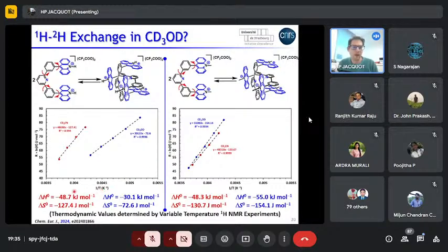Also, we have exactly the same thermodynamic parameters for both systems in acetonitrile and a huge change in methanol. So what we hypothesized is that methanol allows proton-deuterium exchange for the N proton of acridine and protonated acridine, and basically your acridinium core is less electron-deficient, and like this you dissociate the dimer.